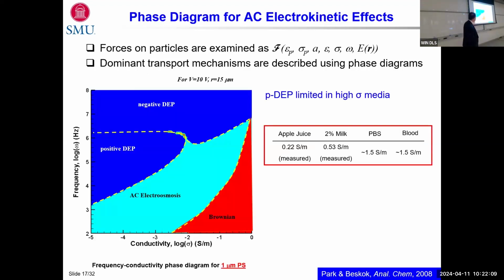So let's see if this is correct or not. So we started to build order of magnitude analysis-based phase diagrams so that we can understand what to expect. So the key is there are 7 parameters here, and I can only plot 2-dimensional. So we fix the interdigitated electrodes with the voltage being 10 volts. Electrode separation is 15 microns. And here's the conductivity versus frequency diagram.